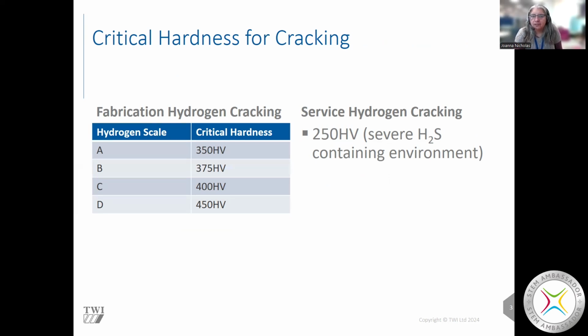And you'll notice that fabrication hydrogen cracking has got much higher hardnesses listed than for service. We can accommodate something more during fabrication than we can during service, and that's to do with the environment in which it's being used. Severe hydrogen sulfide containing environments have greater restrictions because of the way that the hydrogen generated from the acid hydrogen sulfide reaction behaves subsequently.